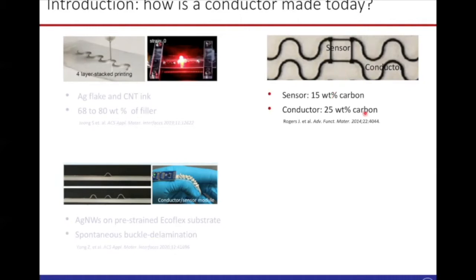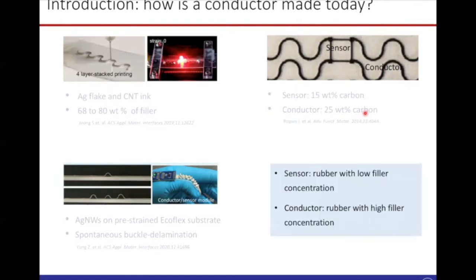Or by using a different filler material. Some materials have a higher conducting property, and some have a lower conducting property, or by changing the filler concentration. So you can play all these games, either changing filler concentration or engineering the structure, to have either a large change in resistance or a small change in resistance. So the overall objective here is to suppress the change in resistance to get a conductor-like behavior. Generally speaking, a sensor with a lower filler concentration should behave as a sensor. And if you use the same filler for the conductor, the general approach is to increase the filler concentration.